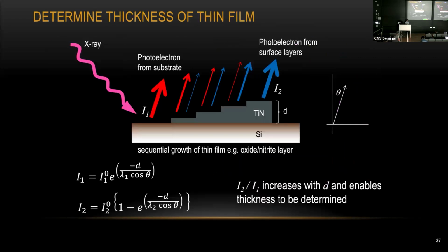You can also use XPS data to determine some thin film thickness. We have a lot of people working in our clean room, and they make multiple layer thin films. Sometimes you're not sure what your thickness is for each layer, so you can come here to the XPS measurement and use some simple model as shown here to determine how thick you have for each layer.